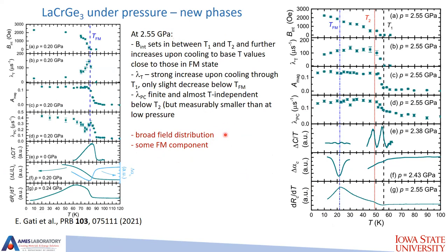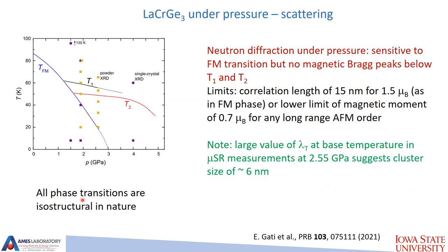So let's remember two things: that there is a broad field distribution as seen through lambda T from muon measurements at 2.5 GPa in the new phase, and also there is some ferromagnetic component, although maybe smaller than at zero or a low pressure, below T2. Let's add here scattering data. So X-ray scattering was done in all these points.